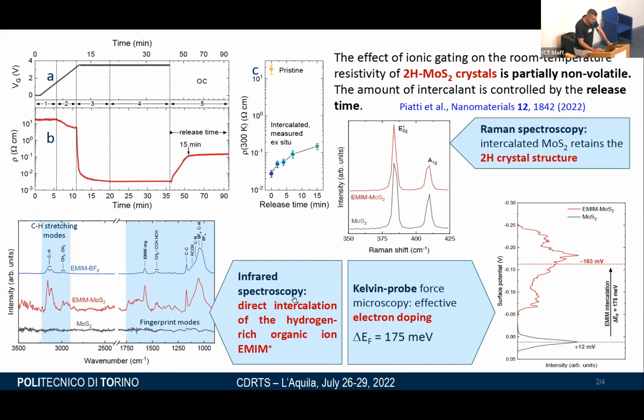So this is the result. This is the gate voltage as a function of time. First, we started from 0, then we made a ramp up to 3.5, and then we kept it constant. The resistivity of the sample first did not change, then decreased a little, and then made a big jump to a value about 3 orders of magnitude smaller than the initial one. Then when we just disconnected the gate terminals without removing the sample from the liquid, the resistivity started to increase again, and then saturated. Clearly, this means that something happens during the gate that is volatile, but something remains. And how can we control the final doping?